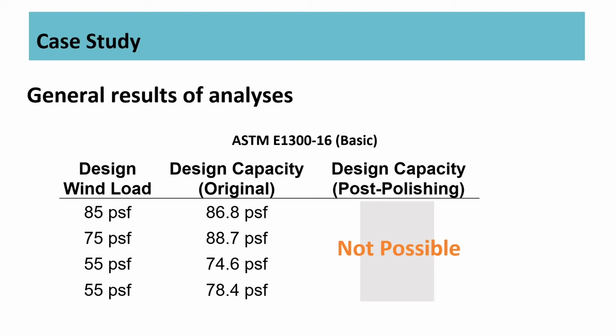It's also worth mentioning that those pre-calculated charts are based on the C1036 minimum thickness standard for float glass, which in practice we find that most glass is often a few thousandths of an inch thicker than the minimum. And so right there, we know that we already have some extra residual capacity. But again, that's one of these things that we can't assume. As our production lines get more efficient, I anticipate that extra residual above the minimum is probably going to reduce to much closer to the minimum than it already is. But that's just my opinion. Somebody else probably could speak more to that. So we can't do anything here.